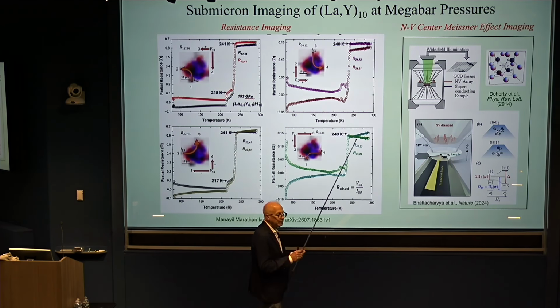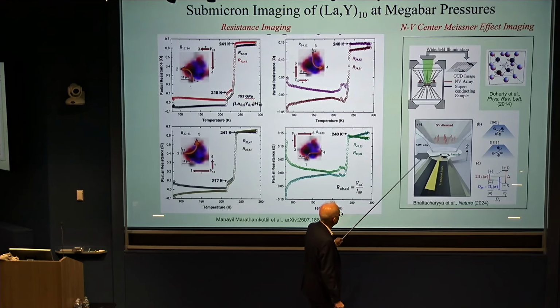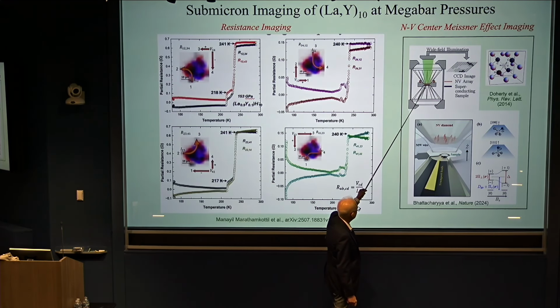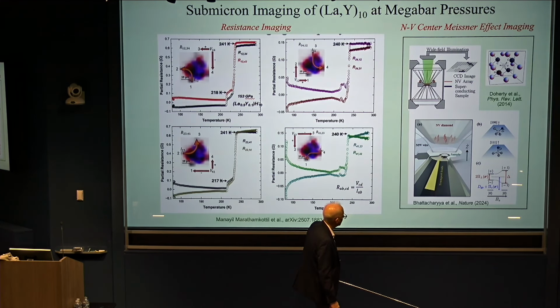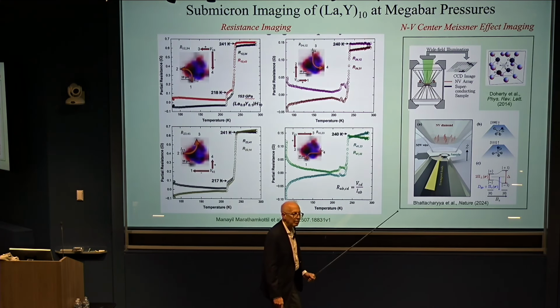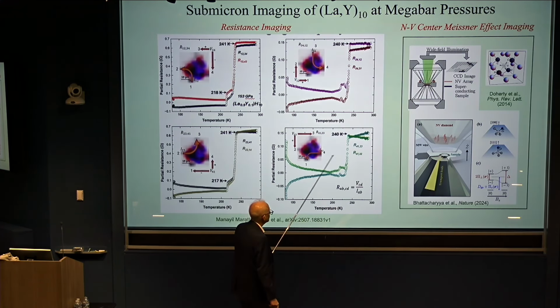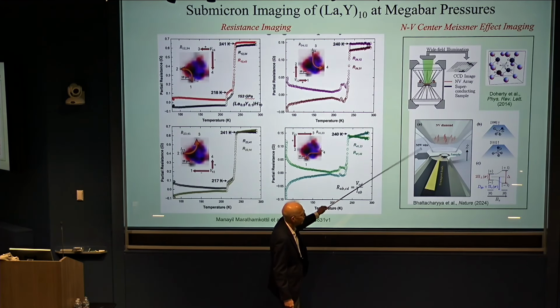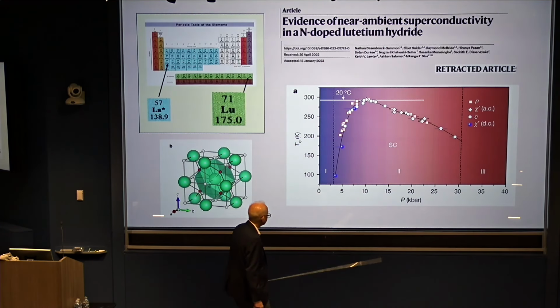And so this ability to spatially resolve what's happening in these high pressure cells is very important also for looking at the Meissner effect, where one can use NV centers, which are little magnetic probes in the diamond. This is something we did years ago, and that's now been implemented in very nice experiments being carried out at Harvard by Norman Yao's group, where they could do Meissner effect imaging of these samples also under these same conditions. And then the goal is to combine this also with the X-ray diffraction.